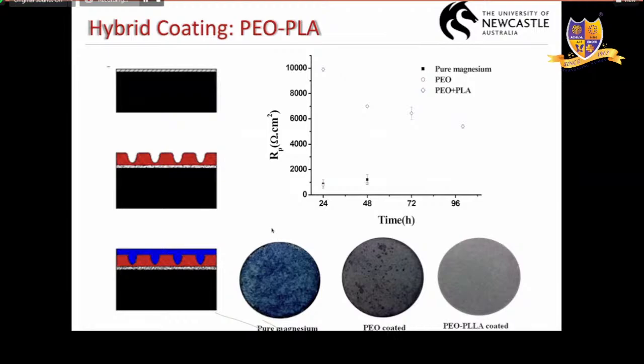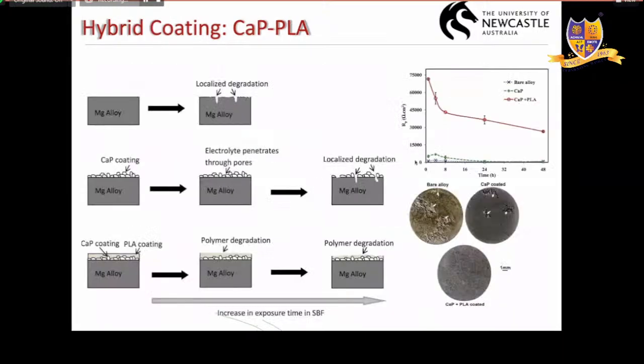And see, this is a slide showing a polymer coating sealing those pores, and the resistance is pretty high in this case. We also did some calcium phosphate coatings on top of that, and similarly, that also showed high resistance. Yes, you can see the difference in the resistance provided by this coating over a period of time. The initial resistance is much more important, whether it is for 3 months or 6 months. The initial resistance is very important.